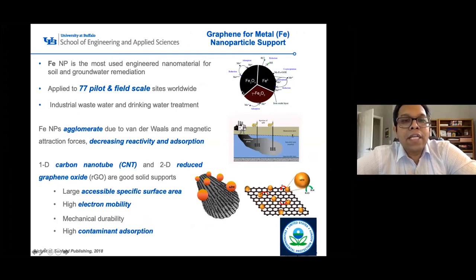And iron nanoparticle is typically the most used engineered nanomaterial for soil and groundwater remediation, and they are applied to 77 pilot and field scale sites. The main advantage is that iron can be in iron zero form or in different redox forms, right? Iron 3+ and iron 2+. So they can move between these forms, and you can have adsorption or catalysis or reactions to treat different organic and inorganic contaminants at the same time using these iron nanoparticles.